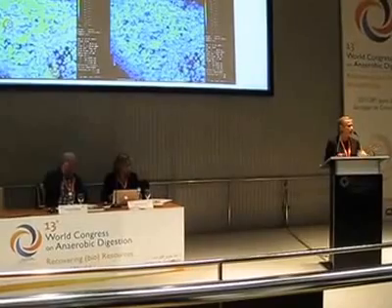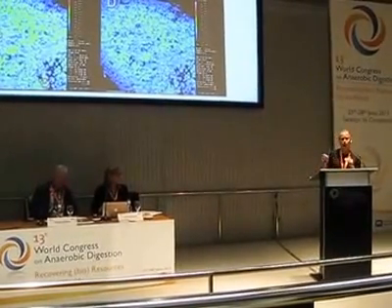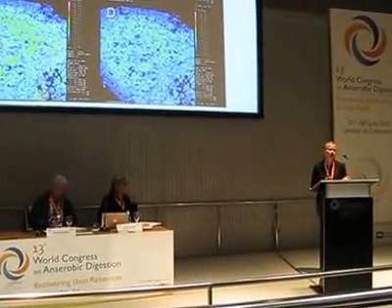In fact, the presence of these separate calcium carbonate crystals could be the key factor why this calcium phosphate precipitation occurred in these granules, since the presence of seed crystals significantly reduces the energy needed to nucleate, and therefore induces the precipitation. However, the carbonate content of these granules is less than 5%, so we are still left with relatively pure calcium phosphate.